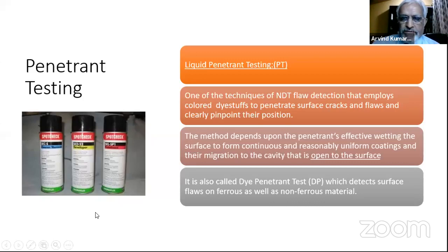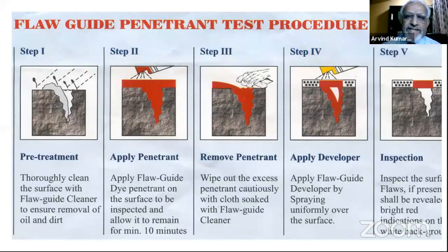So this technique is normally applied to detect surface and subsurface defects, and the subsurface defect should be open to the surface. If it is not open to the surface, then you will not get any indication in penetrant testing. So that is one of the things that you have to keep in mind always. This is also widely known as a dye penetrant test or a liquid penetrant test, but in ASNT terminology, we call it penetrant testing. Now it has 5 basic steps, as you can see, and I will explain.